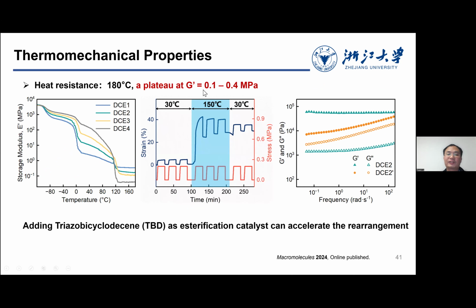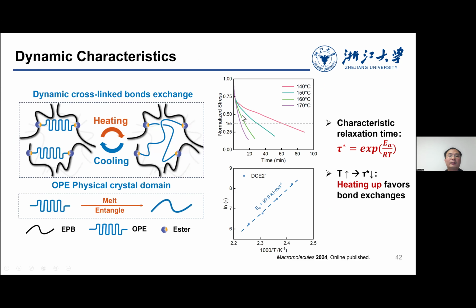They also have good heat resistance. For example, here you can see they still have a storage modulus of around 0.1 to 0.4 megapascal, even at a high temperature of 180 degrees C. I think I'm almost done here. We can also study the activation energy, and here the activation energy is much higher than what we showed in the slides before. The reason is that this network becomes more complex, and the content of functional groups is less than what we achieved in the previous part. But anyway, they can still be processed. In this way, we can achieve a recyclable elastomer based on dynamic cross-linking with waste polyolefin materials.